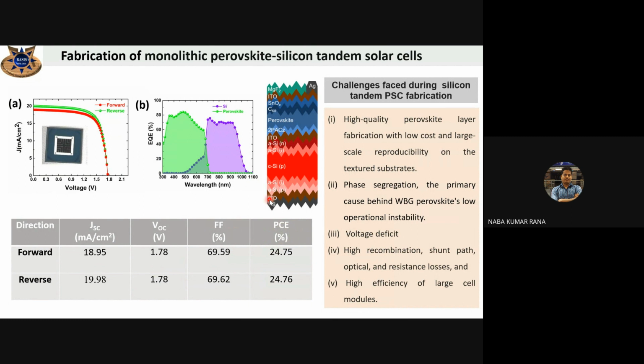There were various challenges faced during this fabrication because we used silicon with a textured surface. On top of the textured surface, deposition of a uniform transport layer is very difficult. It is clearly shown here that this is the texture architecture, and on top of it, smooth deposition of ITO, the hole transporting layer, the perovskite layer, and then the electron transport layer is a very difficult task. So the key challenge faced during this fabrication is the uniformity of the perovskite layer. It's a big challenge. Also, in the case of a wide band gap semiconductor, the deposition is very difficult.